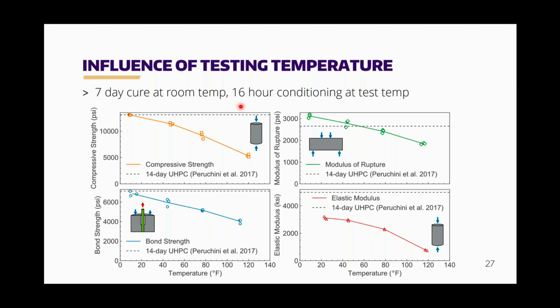Again, compressive strength, modulus of rupture, bond strength, and elastic modulus. We're seeing a similar trend here, similar to what you would see with other polymer concretes, is that at low temperatures, you're seeing higher strengths, and at high temperatures, you're seeing lower strengths. We used 4 testing temperatures here, one a little bit warmer than 0 Fahrenheit, one around freezing, so about 32 to 40 degrees, one at room temperature, and then one around 110, 115.